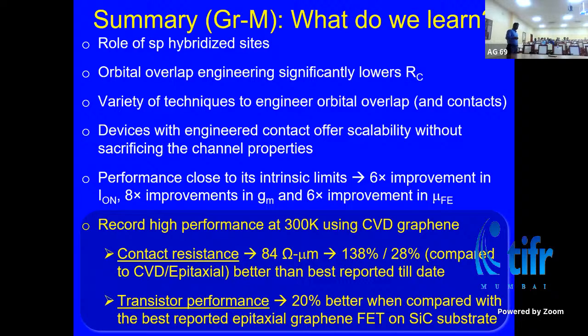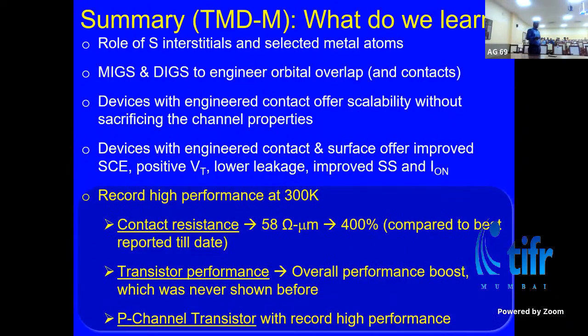And in terms of transistor, we also reported better performance compared to the best numbers reported, and that too compared to what was reported for, say, epitaxial graphene on silicon carbide. In case of TMD, I talked about these S interstitials, surface interstitials, and the selected metal atoms. And that introduces these gap states, or these states introduced in the mid-gap region, which are triggered by the metal and the defects.